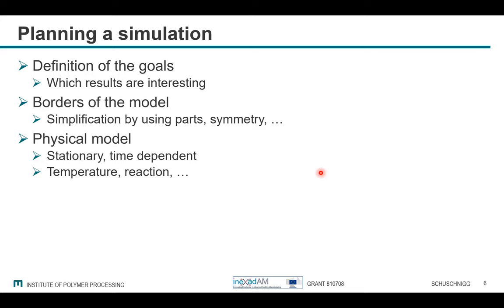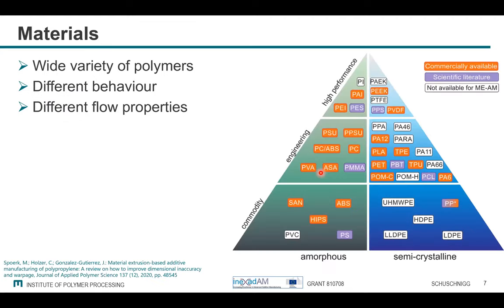On the other hand, with one simulation we had to simulate the whole construct, because then the flow lines were more important, so that we can see the residence time distribution inside. Can we use a symmetry? Do we have other physical models where we can state something a little bit easier? For example, stationary: in extrusion it is mostly stationary, while in injection molding, which Tom is talking about afterwards, he often has a time dependency inside. Is there any temperature to look at? Are there any reactions, for example crystallization or chemical reactions? I can make simulations really, really hard, taking everything into account, but mostly it's not feasible, because you don't have that much calculation power or the material data.